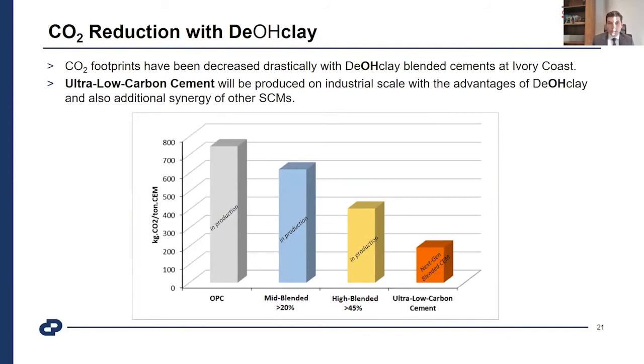When we look at the CO2 footprints, as you could see, the DeOHclay blended cements are in existing production at the Abidjan plant, compared to CEM I and the other mid-blended and high-blended products. Our aim, as I explained in the previous slides, is to use low-carbon DeOHclay and also additional supplementary cementitious materials, and we checked that we could achieve less than 200 kilograms CO2 per ton of cement. It will be a specific product, as our chairman explained. We are planning to introduce it to market at the end of this year or the beginning of next year.